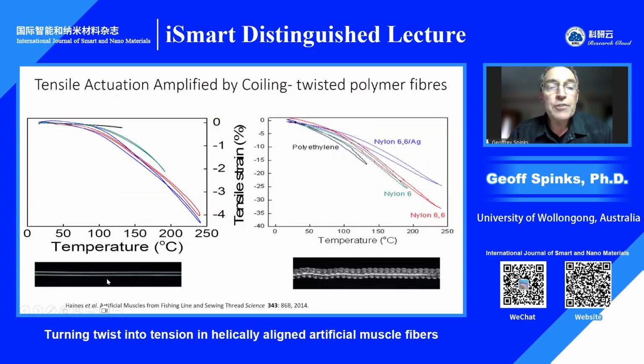Just how well? Well, that's really emphasized in these results shown here. So what we're seeing on the left is the tensile strain of the textile fibre as received during the heating from room temperature to, well, approaching the melting temperature. We're looking at some nylons down here and a polyethylene fibre up the top there. So you can see this is the as received, highly oriented textile fibre, not twisted at all, just as received.